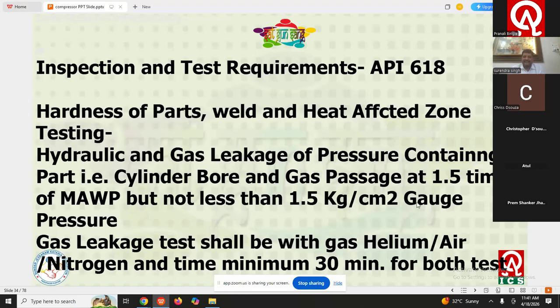This is a condition given additionally, if my compressor is working at a very low pressure, say 0.5. As per the rule, the testing pressure must be 1.5 times 0.5, so the testing pressure would be 0.75. But for that case, the condition is given that even if the pressure is so low, the hydraulic testing shall be at least 1.5 kg per centimeter square.